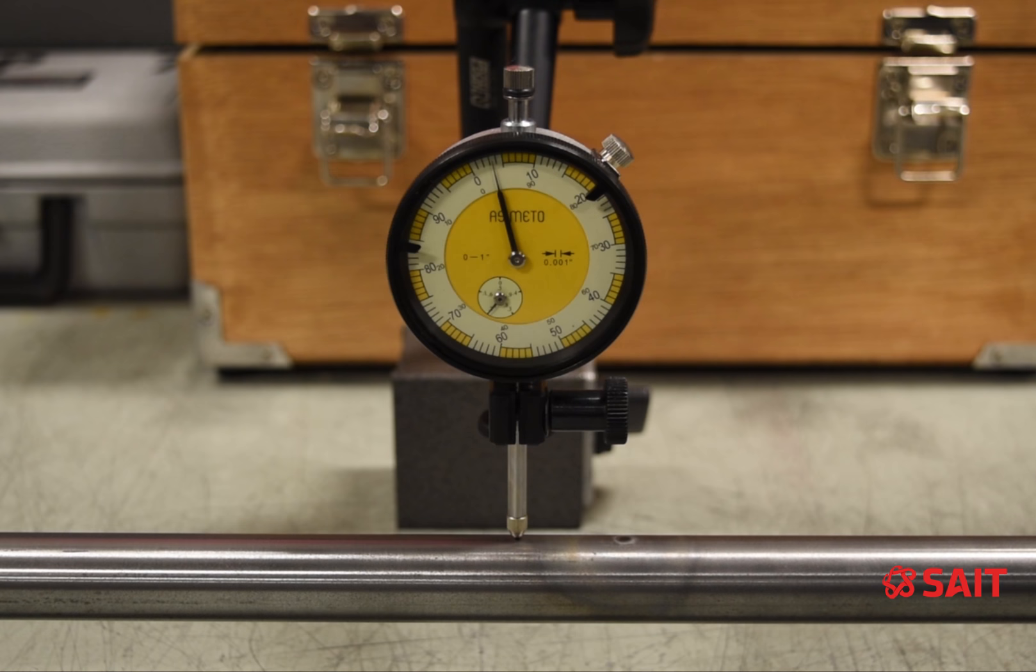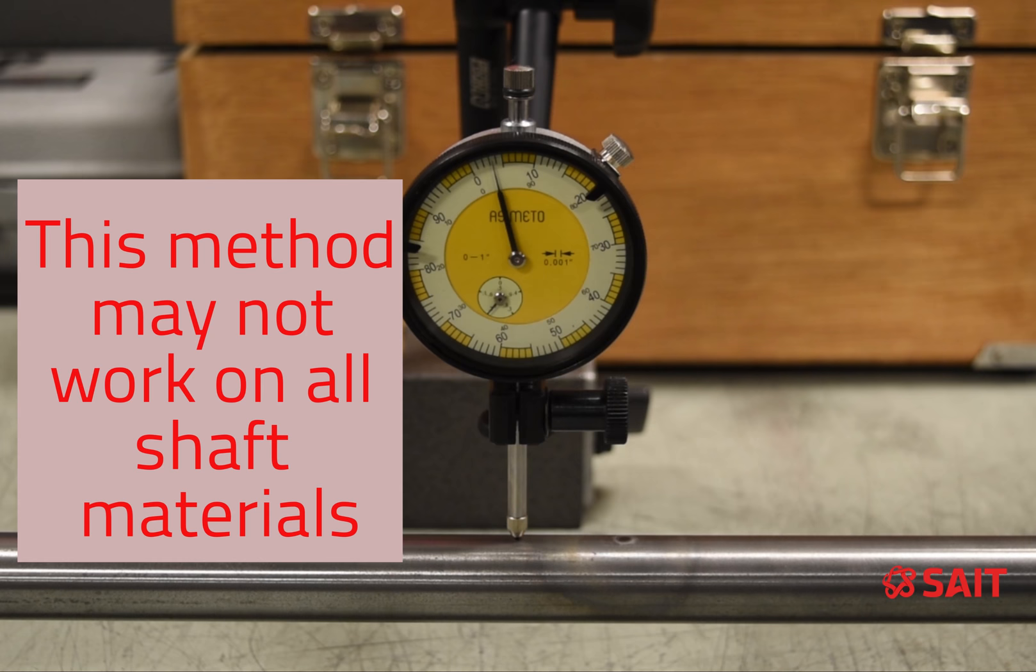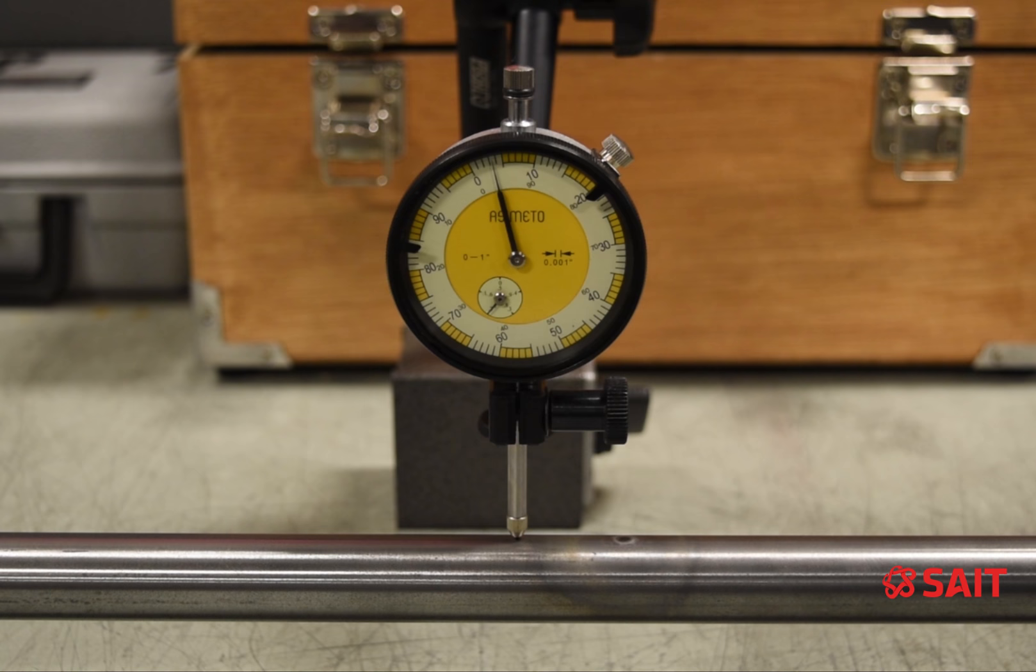There are some things to note while this shaft cools. Number one, if this is a heat treated shaft, this is not a method to be straightening the shaft with, as this will take the hardness out of the shaft surface.